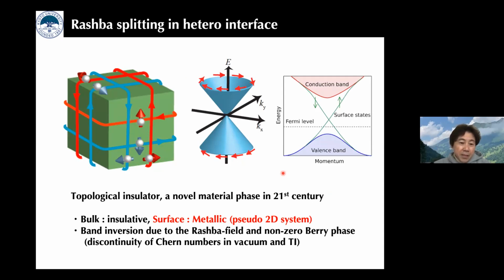So now some of the audience may wonder what the heterostructure is here. Here I emphasize that this heterostructure is a topological material and vacuum, because the Chern number, namely the Berry phase, of the topological insulator and vacuum are not continuous. And because of the discontinuity of the Berry phase, twisting of the wave function takes place, which allows a spin polarized Dirac-like linear band at the surface of the topological insulator. And spin momentum locking can be induced by this unique band structure as shown here. And this is the reason why millions of people are attracted by this material.